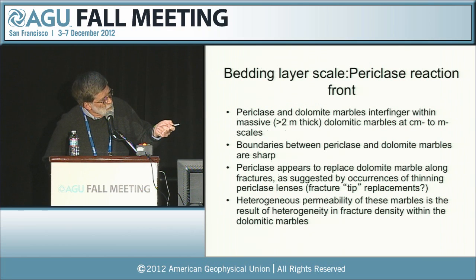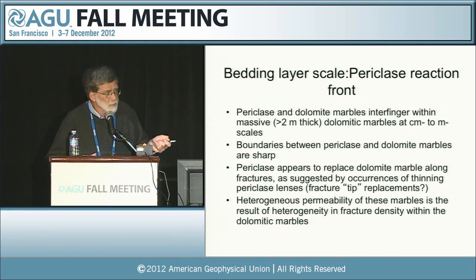I've got a few minutes to show you some observations on the Periclase reaction front. Normally the Periclase front is a fairly narrow front, but there's a certain area where there are some unusually thick, pure dolomitic marbles, and in those areas the Periclase and the dolomite marbles interfinger at centimeter to meter scales. The boundaries between the layers are pretty sharp, as I'll show you in a second. This replacement seems to be fracture controlled at this scale, so I think in this case the heterogeneous permeability of these marbles is a result of heterogeneity in the fracture density within the dolomitic marbles.